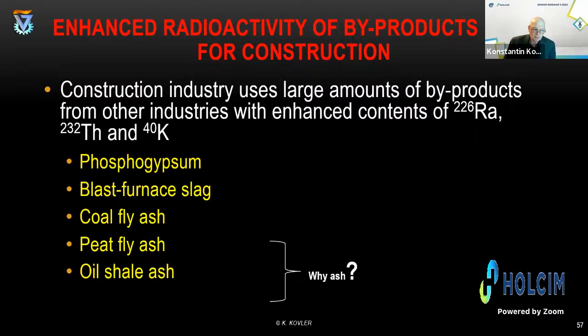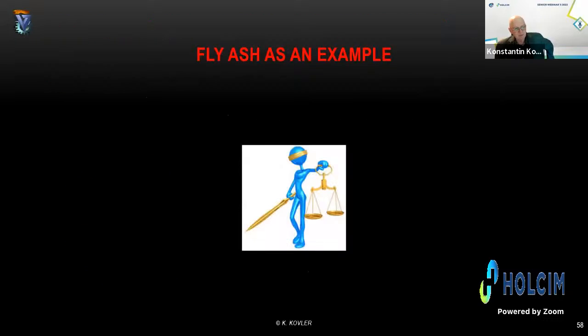Most of the material is lost because we produce energy, we produce vapor, we produce steam, and then we produce, let's say, from this coal, something which is not mineral, which is organic matter. Organic matter is completely fired, is lost. And then what we have in the end is inorganic matter. This is our ash. If I speak about coal fly ash, 90% of the material is lost, which is organic matter in the coal, and only 10% is left as ash. In this 10%, we have so-called enrichment of all inorganic matter, like metals, heavy metals, and radioactive metals.